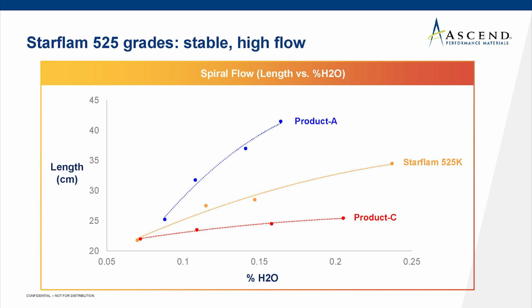So it might be a little bit difficult to dial in the molding conditions with varying moisture. And then if we look at product C, it's got a very flat curve, so it's not responding a lot to moisture, but then its flow is not very good. We view our Starflam 500 series as being a balance between having high flow and lower response to moisture.